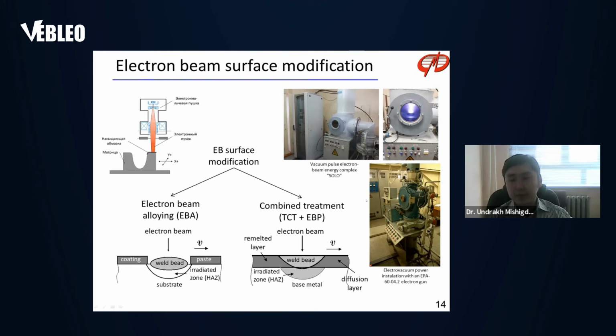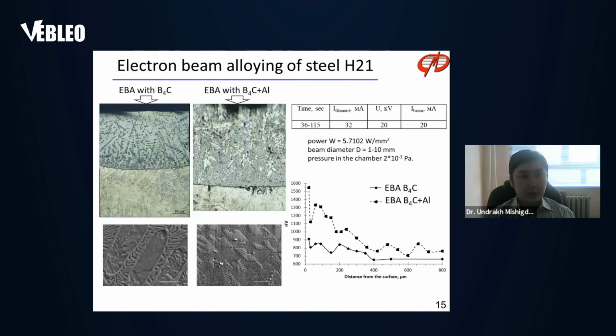The results in the present research will be from results obtained on this second installation. Electron beam alloying resulted in coating formation with a thickness of around 300 to 500 micrometers.